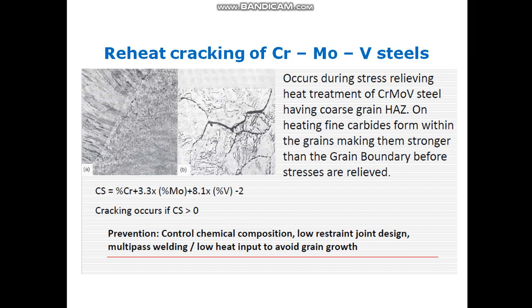Now to assess the susceptibility to reheat cracking, there is a parameter known as cracking susceptibility. It is known as CS equals percentage chromium plus 3.3 times the percentage molybdenum plus 8.1 times percentage vanadium minus 2. When we put in the values of this composition of chrome, moly, vanadium, if the CS value is greater than 0, then cracking occurs. So how do we get away from this reheat cracking problem?